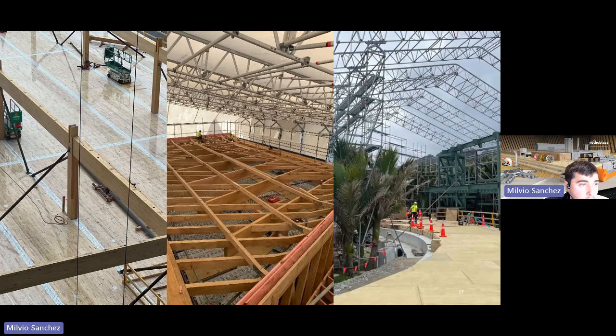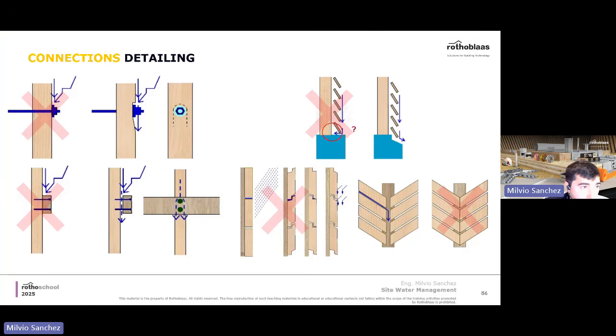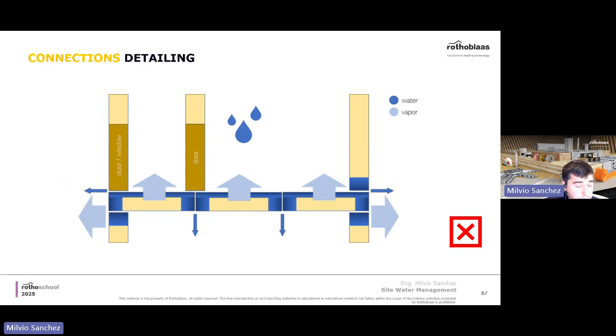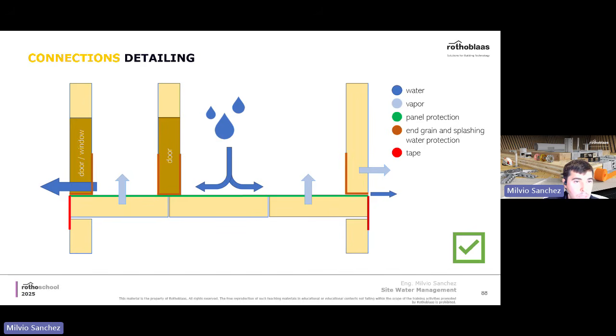So here you can see some photos of successful, very interesting projects where tenting has been used. And lastly, the connection details, right? Very small changes in direction, very small curvatures, or not having sharp edges can allow moisture to not get trapped, and your connections are not going to suffer from this moisture absorption. It's clear that the end grain is much more critical than the side grain, but it doesn't mean that the side grain is negligible in terms of moisture. So ideally, the condition here to protect this panel configuration is taping the end grain, panel protections, temporary or permanent, over the CLTs, and splash and water protection where needed as well.